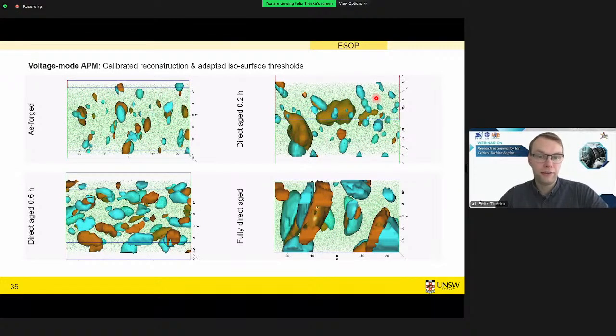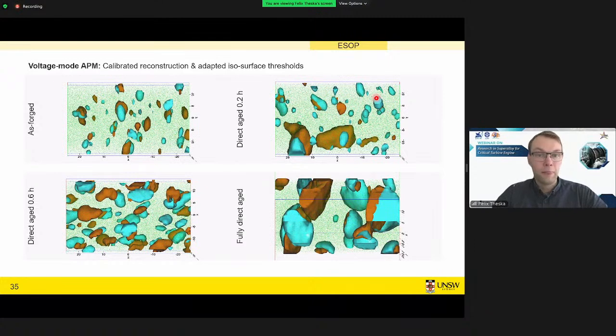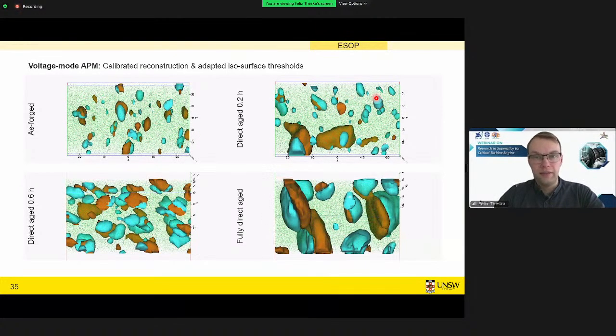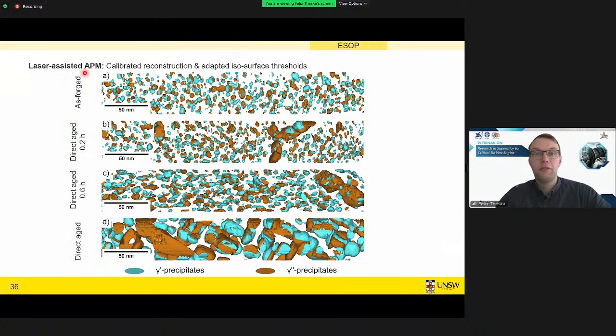But these are large enough to get some precipitate size descriptors so that we can calibrate our large-scale data, as you can see here. And indeed, in the as-forged condition, we have a high density of small particles, which looks very similar after the 0.2 hours direct aging condition.